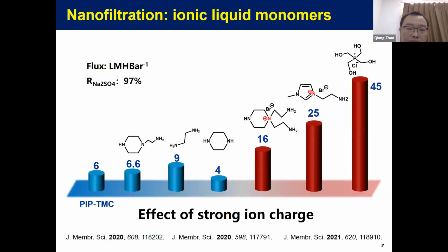We proposed a series of new monomers. If we look at the blue columns, which are conventional monomers, you will see the permeability, or permeance, of membranes made from these monomers is usually between 4 to 10 liters per square meter per hour per bar. But when you introduce strong ions into the monomer, like the three red columns standing on the right, you will see the flux improve drastically. I will not go into details of this work. If you are interested, you are referred to the paper cited right here.